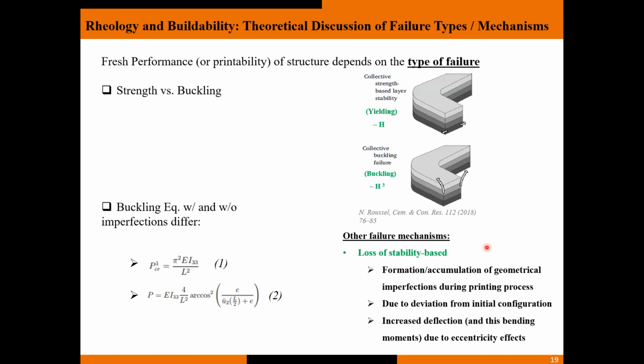And what happens is that from accumulation of geometrical imperfections, as was shown in the previous work, you typically end up with additional bending moments and accumulation of eccentricity, which then leads to local buckling and then global buckling. And the question is, which rheological properties is responsible for buckling specifically?